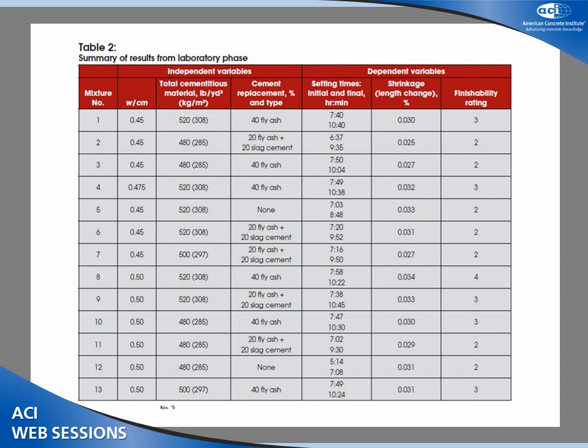Here are the mixes that we tested in the lab. There were 13 of them. You can see in this column, well, the first column is the water cement ratios. The second column was the total cementitious, 520, and we had several at 480. We were pushing the limits of the total cementitious, again, in our effort to make it as green as possible. Like I said, and I firmly believe this, we've been over-cementing our mixes for decades. So the highest total cementitious we had here was 520, and many of them were 480.